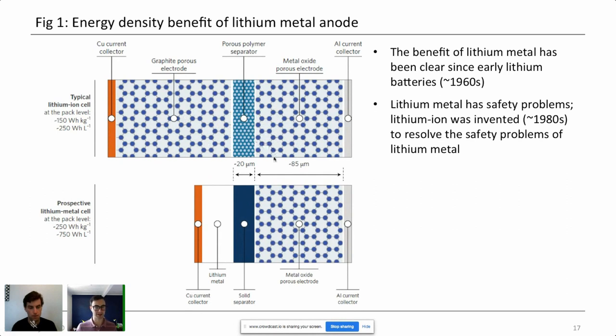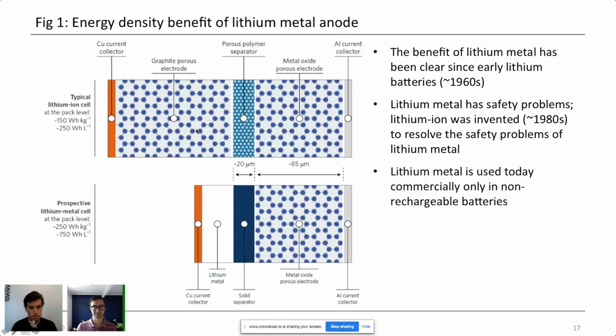So lithium will cause a safety problem and grow what's commonly referred to as a dendrite if you don't take special precautions. So today, lithium metal is used only in non-rechargeable batteries, where you're never having to what's called plate this lithium back on the anode side when it would like to grow in this high surface area structure. It's used only in a non-rechargeable primary battery, where you strip the lithium from the anode side, remove it from the anode side, deposit it into the cathode. And if you do that only once, then it's safe. And it's actually used in a lot of watch batteries that you might buy today. But if you recharge it, that's when the problems start to occur.